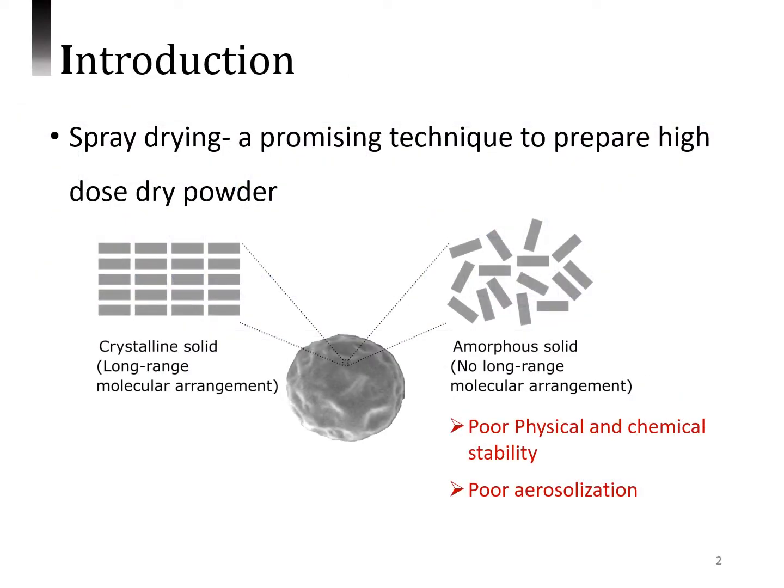High-dose dry powder antibiotic inhalation is becoming a standard in the treatment of bacterial infection in different pathophysiological conditions, such as cystic fibrosis. Among the different techniques which have been explored to prepare high-dose dry powder, such as direct crystallization, milling, supercritical fluid techniques, etc., spray drying is emerging as a promising technique, particularly because of its ease to modulate both particle size and morphology. In addition, reproducibility and scalability are its other advantages.